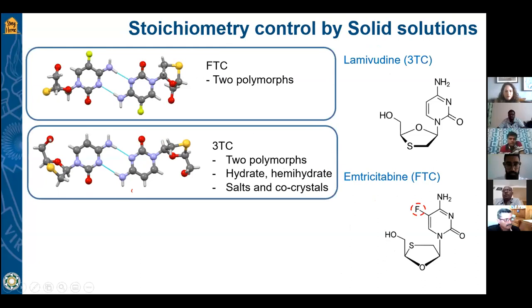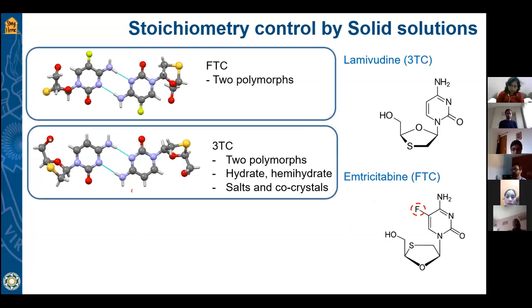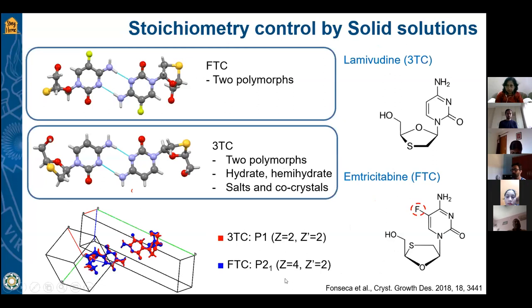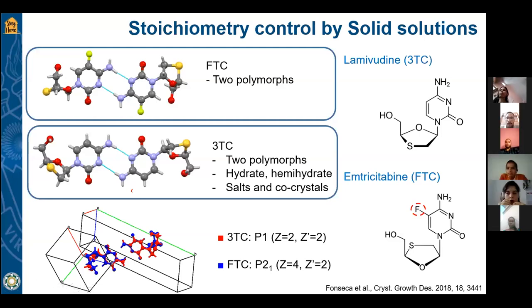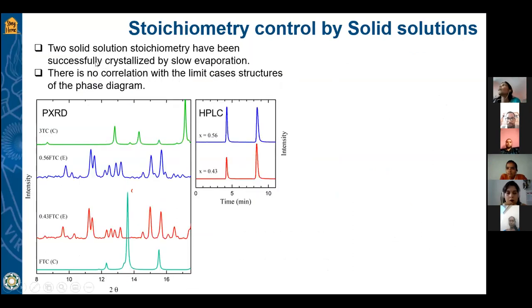at the moment of design for a solid solution, we are expecting some kind of isomorphism between the two molecules. So if we compare the structures of both of them and overlap them, you can see that even if they don't have the same crystalline structure, they share the same packing, and it could be a signature that they could get a solid solution. So due to that, we tried to produce the solid solution by slow evaporation,